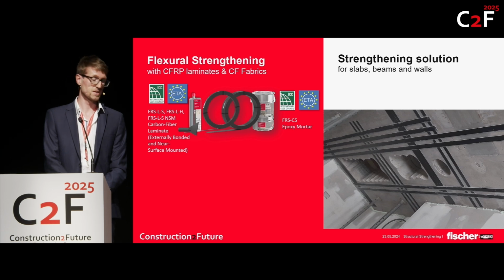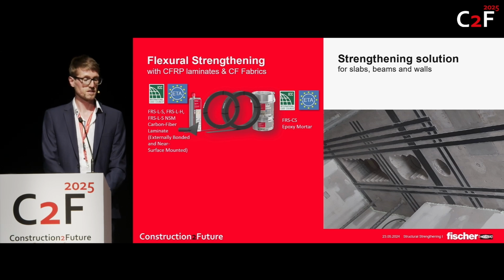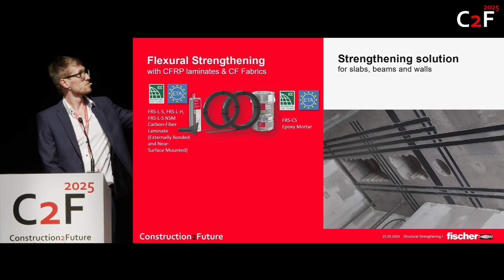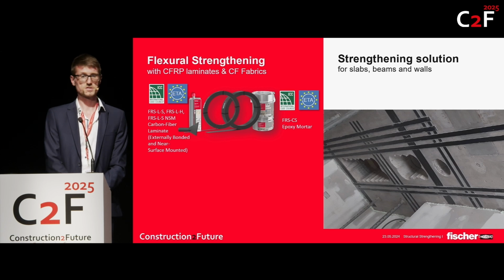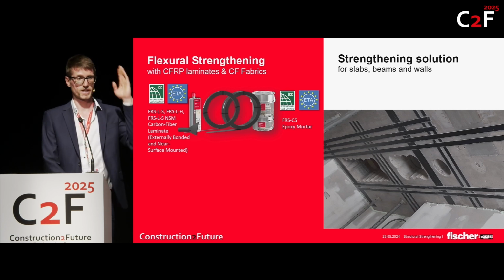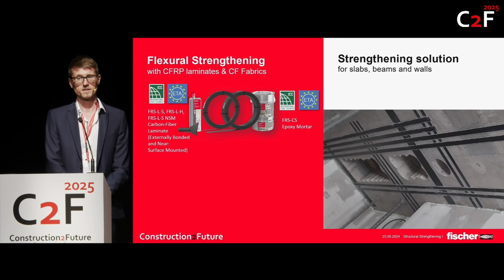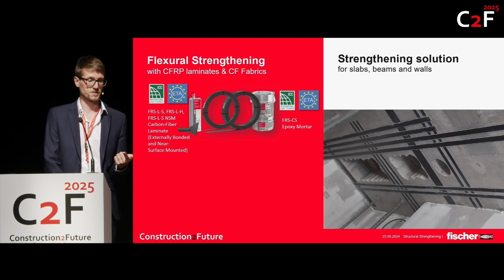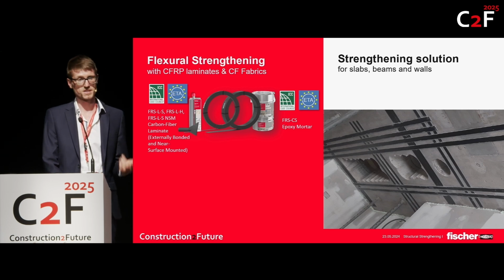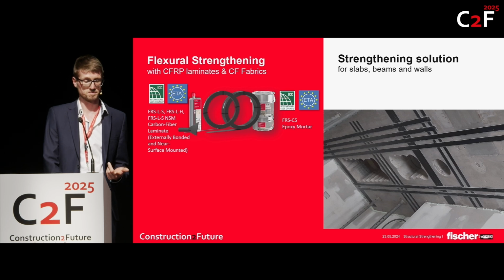laminates. It comes either in buckets if you want to do externally bonded application, or in cartridges for near surface mounted. It comes with a specifically developed adapter, so you can use the normal Fischer mixing nozzles to simply inject the epoxy resin into the groove and save time, be fast in the construction, and have a clean and tidy construction site without any pre-mixing of epoxy resins, filling it into tube bags and then injecting it into cracks, which is a mess.